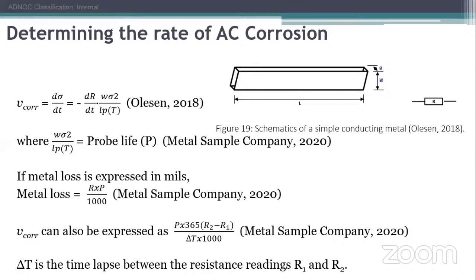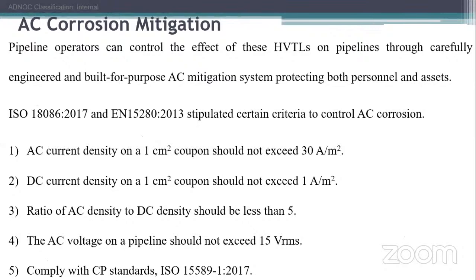So this is a formula to know the rate at which this AC corrosion is progressing. We can also protect our pipeline from this form of corrosion. If we are able to make sure that AC corrosion does not exceed 30, then our line is safe. If the DC also does not exceed 1, our line is safe. So these measures just guide us.